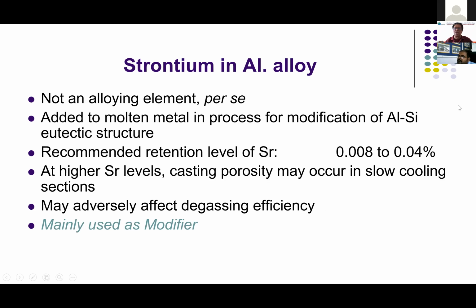This addition of strontium helps, we can have very good ejection properties of PDC components at 0.7% iron with 0.01% strontium. It improves the removability from the casting. It reduces the affinity of the casting to stick to the die. It doesn't allow the casting to stick to the die. 0.01% of strontium, if I remember correctly. I have to go through my notes again and come back. So therefore, even in PDC alloys, you can drop the iron below 0.8%, keep strontium, a small quantity, it will give you the same very good effect in releasing the casting from the die.